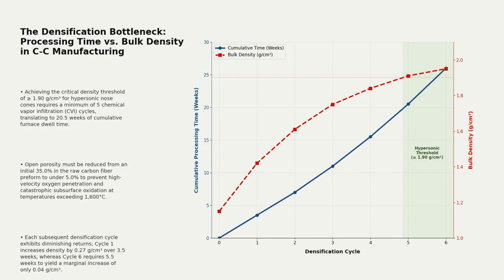Hypersonic flight requires structural materials that survive extreme atmospheric friction. Carbon-carbon composites are the industry standard, but their manufacturing is constrained by physics. Achieving a density of 1.90 grams per cubic centimeter requires 5 chemical vapor infiltration cycles. This process demands over 20 weeks of continuous vacuum furnace dwell time.